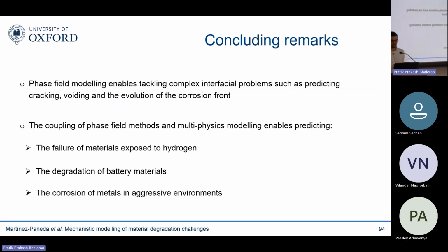Okay, and just finishing just on time, some concluding remarks. I will just say that I think we do have a very exciting opportunity in front of us. I think that the combination of phase field modeling of interfaces and this kind of coupled multi-physics models allows us to finally resolve the underlying physics of many complex phenomena, such as fracture, voiding, and the evolution of the corrosion front. And the good thing about it is that you eliminate assumptions, you eliminate fitting parameters, and you can deliver predictions that are basically resolving the underlying physics as they happen in reality.